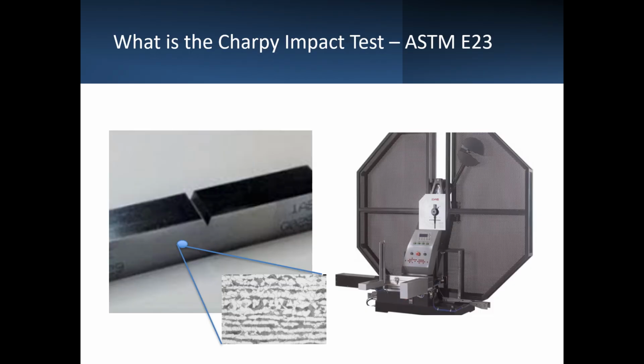So what is a Charpy impact test? The traditional thing that happens in the industry is we buy in 10025 J2 material, we conduct a set of Charpy impact tests. They happen to pass the 27 joule requirement at -20 on this machine. Here you can see a sample of a Charpy impact test specimen, very nicely machined to tolerance with a notch in it. On the right-hand side, you can see the Charpy impact testing device, which is the one that we had downstairs.